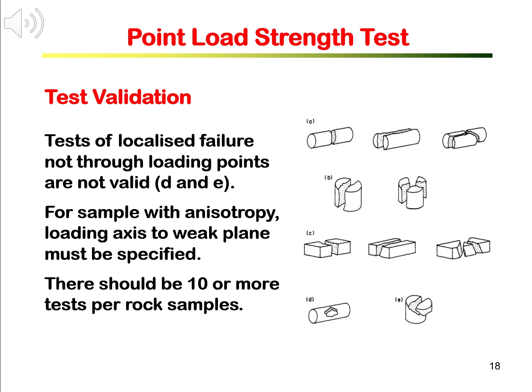Not all the point load tests are valid. Tests with specimen breaking across the whole thickness through the loading points are considered valid, and the strengths determined are acceptable. Tests of localized failure, not through the loading points, are not valid, as those shown in D and E in the right figures. For samples with anisotropy, the loading axis to weak plane angle must be specified.